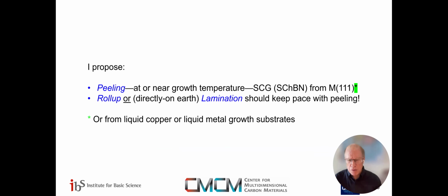So what I propose is a new research effort needs to be started on peeling at or near the growth temperature, ideally, so we don't slow things down by cooling down to room temperature and then warming back up. And this could be as noted on those metal 111 surfaces, or it might be from a liquid metal. And then the roll-up or lamination should keep pace with the peeling, otherwise it becomes a rate determining step. In this talk, I will assume that it is keeping up with the peeling.